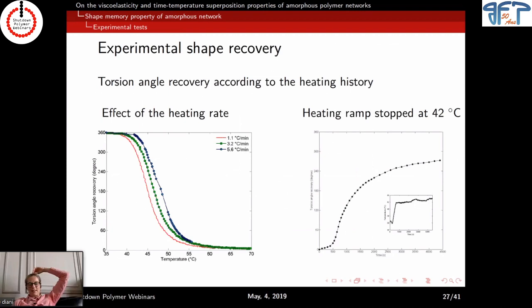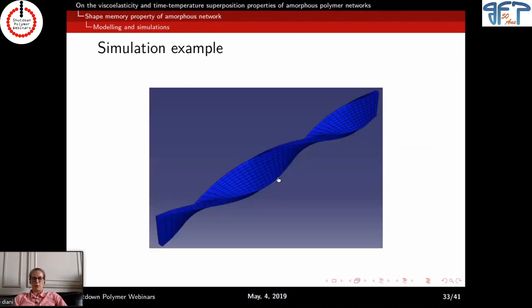I guess the thing is that if you applied right away a high temperature, you just need to take into account the diffusivity of temperature in your material. We haven't done that. I could apply, for example, on my finite element. If you see, here I applied the same temperature on all the nodes. If now I just apply it on the surface and have a conductivity coefficient for how the temperature changes over time, I would be able to do that. There's no problem for that.